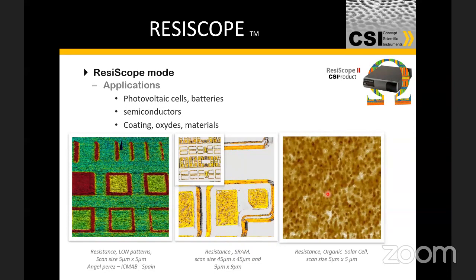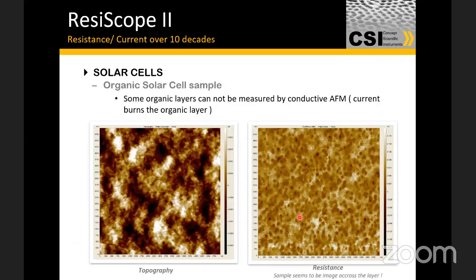The surfaces themselves are quite soft, and this is another critical point in AFM measurements: if tips end up damaging your surfaces, then obviously you can't make a reliable measurement. With things like organic LEDs and organic solar cells, this is quite a critical factor, because by nature they're organic surfaces and they are quite delicate. So you cannot probe these surfaces and in the process damage the surfaces themselves. So we have to use some clever measurement techniques to be able to look at soft electronic surfaces, or organic electronics. And I'll come to these in the next 5-10 minutes, hopefully.